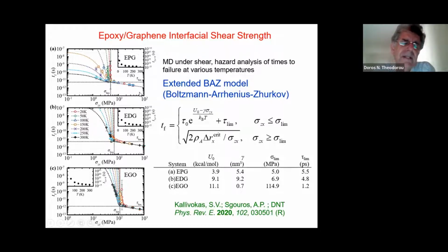What happens here is that the interface fails in a barrierless fashion, and the graphene starts accelerating with respect to the polymer, hence this -1/2 power in the dependence. If, however, the stress is lower than this limiting stress, you have a very interesting behavior which suggests a thermally activated process. The time to failure essentially follows what one could call an extended Boltzmann-Arrhenius-Zhurkov expression, where you see that there is essentially an exponential here, which has kT in the denominator, and in the numerator, it has an activation energy, U0, and also an activation volume, gamma, that couples to the imposed stress. The plots of this extended BAZ model are these broken lines, and they describe the results quite satisfactorily.